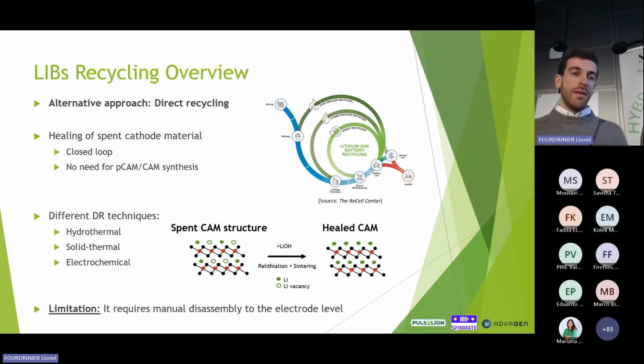Now, I mentioned before that there is one alternative approach, which is the direct recycling. So in the direct recycling, instead of breaking down the cathode structure to the individual metal precursors, the idea is to heal the cathode material as such. So you can see in this picture that you have your spent cathode material at the beginning with some lithium deficiency. So you can compensate this lithium deficiency while maintaining the crystalline structure. So at the end of your process, you will have again the cathode material with no need for the synthesis of the CAM again. This approach is very interesting for batteries containing low valuable materials like the LFP, for instance, because it might not be economically worthy to break down the LFP structure to recover the lithium and the iron phosphate because they are very cheap.